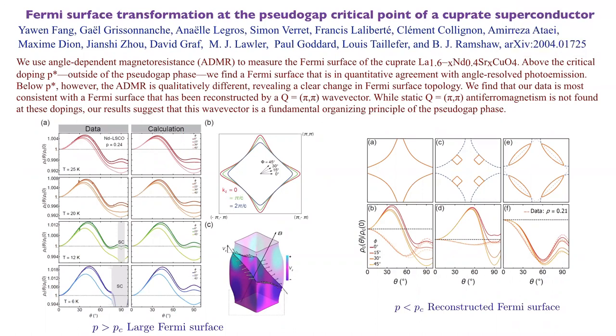So your theory then will distinguish electron doped cuprates from hole doped cuprates, right? Yes. For electron doped cuprates, at some level we don't need a theory. The spin density wave theory would basically work. But even there, if you start looking in more detail right near the critical point, there are issues with it. So some aspects of the physics I'll talk about may also be relevant for electron doped, but they are less relevant. I think for the hole doped cuprates is where this issue is the sharpest and very clear.